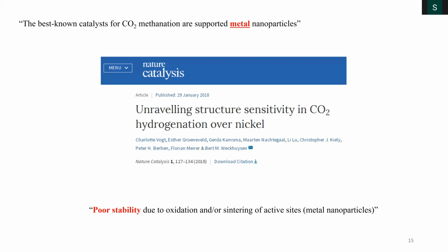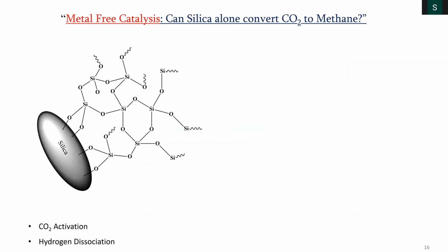So we wanted to solve this problem. Now if I replace the nickel by any other metal, it will have the same issue, right? Most metals are very reactive, but they are also unstable because of oxidation and sintering. So we thought, can one replace the metal by no metal? Can one do a metal-free catalysis of CO2 activation? Then how do I do it? We proposed this hypothesis: can I create defects in my material which will activate the CO2 and dissociate the hydrogen?